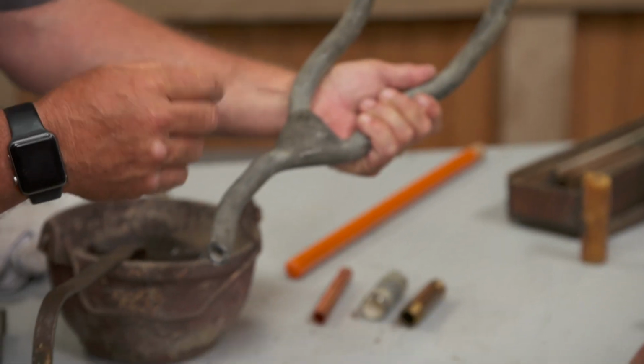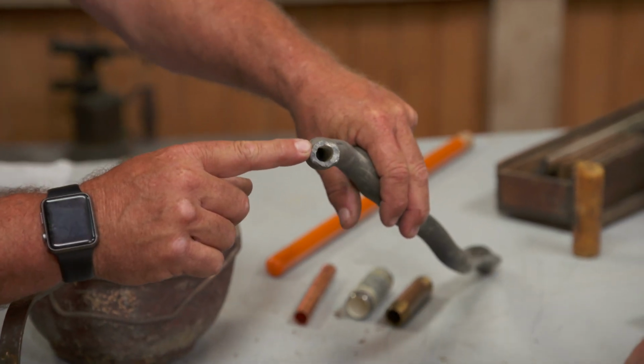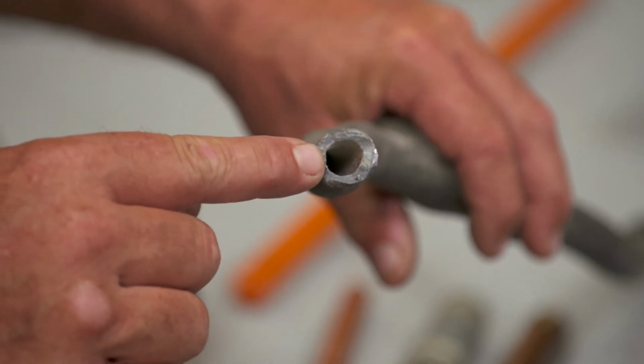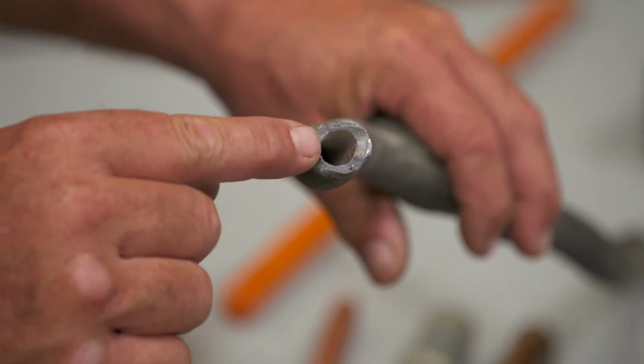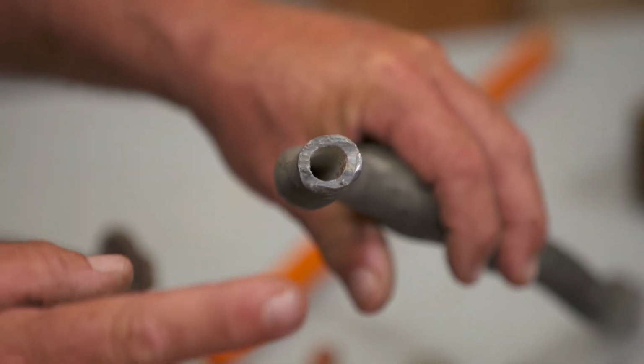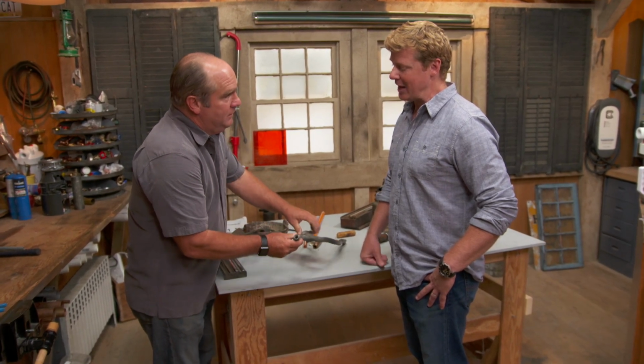Now, in the case of Flint, over time, the lead water mains will get coated with minerals, okay, inside here. So those minerals actually act as an insulator to keep the lead from leaching into the water. Okay. Flint did two things. They changed the water supply and the water chemistry, which made that layer disappear, losing its insulation, so now it could leach into the water. So that's why we got all the problems there.